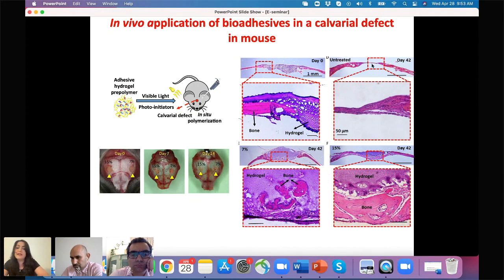And here on the right side, this is the defect we create. This is untreated after 42 days. And these are the defects that the left one treated with 7% hydrogel and the right one treated with 15% hydrogel. So after 42 days, we have higher bone formation for the group treated with stiffer hydrogel.